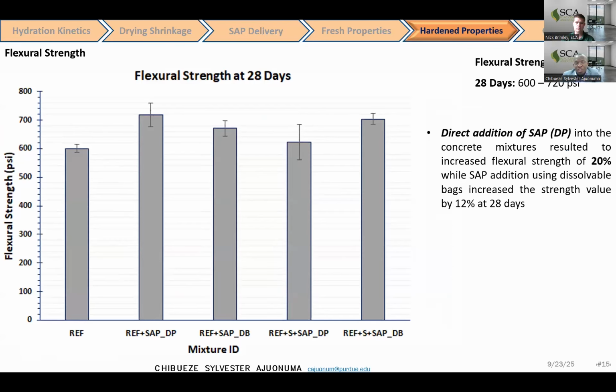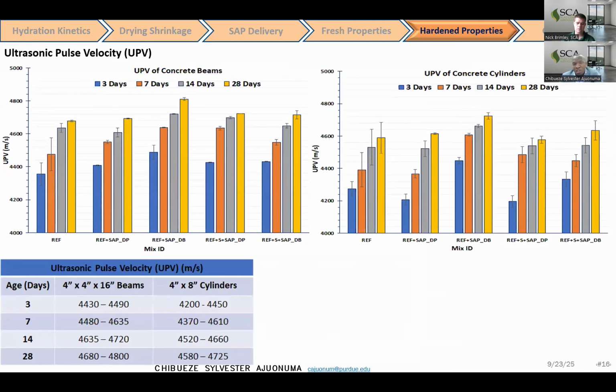Then we also evaluated the flexural strength at 28 days. We also saw similar strength increase with age, and also evaluated the ultrasonic pulse velocity to see the homogeneity of the concrete matrix, and this is a range of the results we obtained for the ultrasonic pulse velocity at 3, 7, 14, and 28 days. We saw a steady increase in the pulse velocity with age, and then also we saw a comparable result between directly pouring SAP and that of the dissolvable bag.